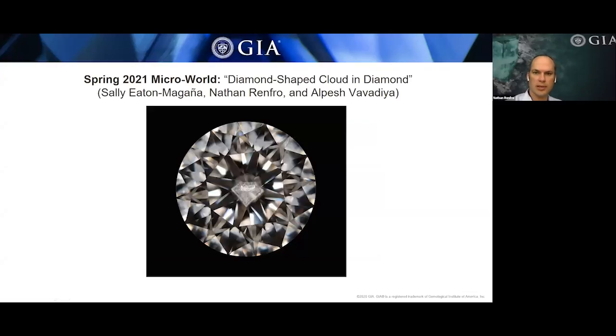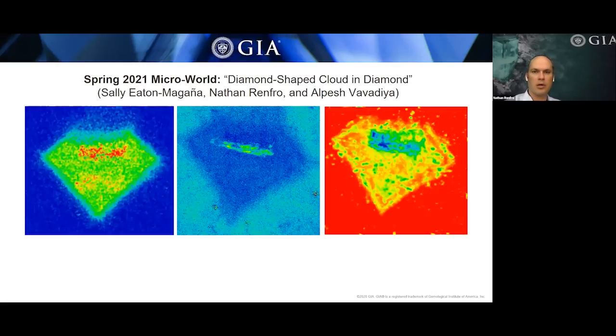Here's what the stone looked like face up. I think it was a rather small stone, about a ½ carat or so, but quite an interesting cloud in that stone. The PL mapping showed in the cloud area a peak around 700, which was consistent with this hydrogen nickel defect.